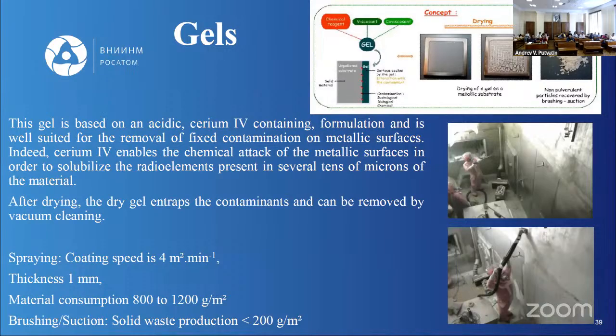This is a variation of polymeric films: the application of destroyable gels. Gels are also applied to the surface from water solutions, and after fixation, after reaction with this surface, and after drying, the gels auto-destroy into small items and can be removed from the surface with just vacuum cleaning. In this case, we have a problem just with solid radioactive waste. We have no liquid secondary radioactive waste.